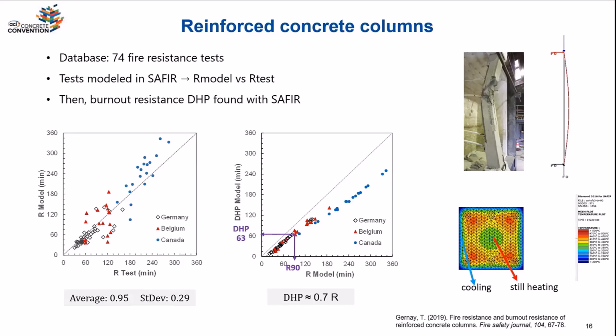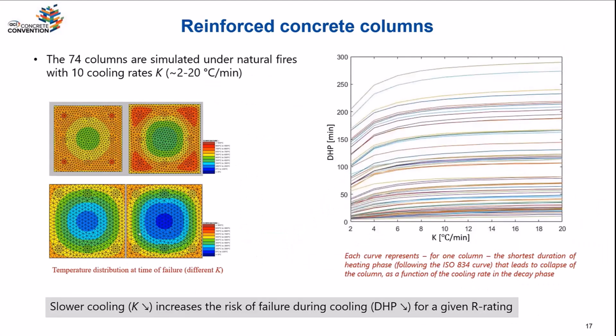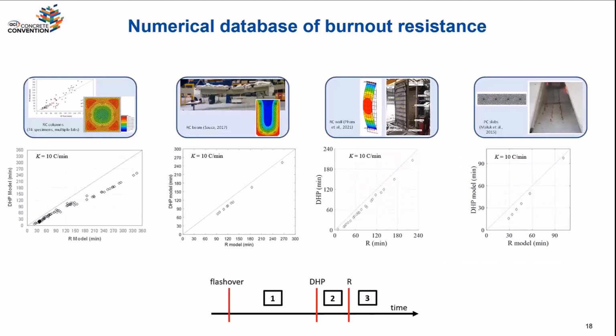So this kind of gave us a framework to systematically quantify the vulnerability to cooling and differentiate between those fires that result in failure eventually and those that are survived. So we did lots of simulations varying the cooling phase and so on, and looking at those different members. I'm going to skip that, but again, conceptually, what we want is to divide the time domain in 3 zones. Everything that's shorter than DHP, of course, this is for standard natural fire, but everything that's shorter is going to be survived indefinitely. If the exposure to this particular standard fire lasts for more than DHP, the member is being exposed to so much heat that it will eventually fail. And then once we reach standard fire resistance with this particular exposure, it has failed.